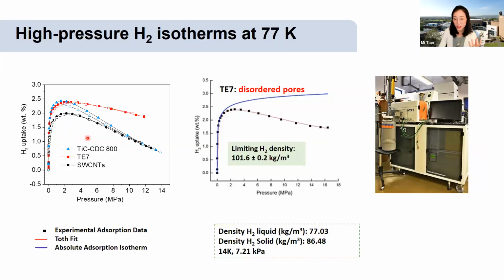In industry, in the engineering field, we really care about how much hydrogen the material can store in total. So we carried out the high pressure gas adsorption measurement. This is the equipment I have been working with in our lab. And this is a high pressure gas adsorption curve. We can read the hydrogen uptake. The maximum is about 2.5 weight%.